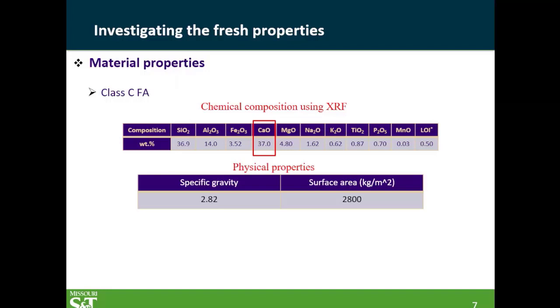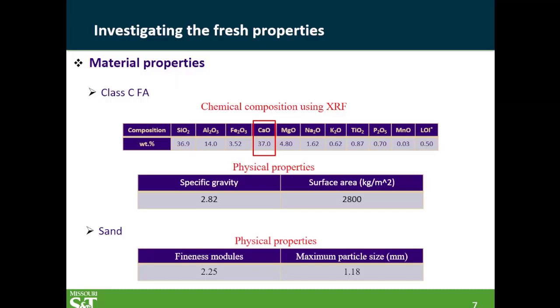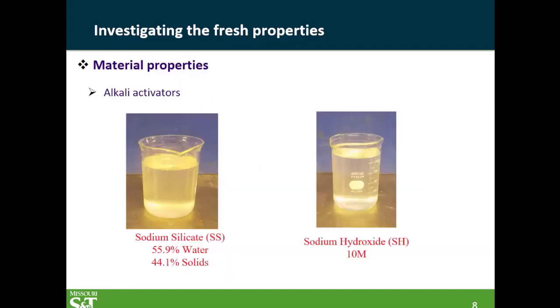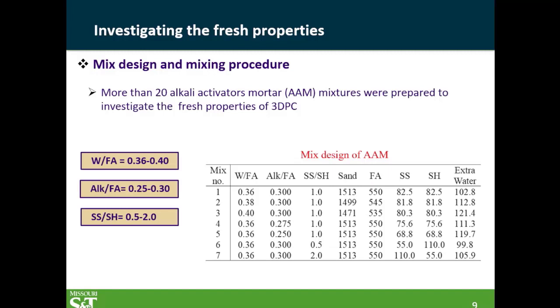For this supplier, we have a calcium content of about 37%. We did also a lot of characterization. Other characterization is not presented over here. And then we have the sand. So this is the alkali activator. As I mentioned, sodium silicate and sodium hydroxide. The sodium hydroxide is 10 molarity. And for the sodium silicate, it's about 56% water versus 44% solids.